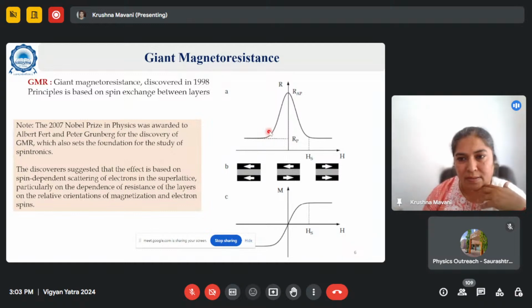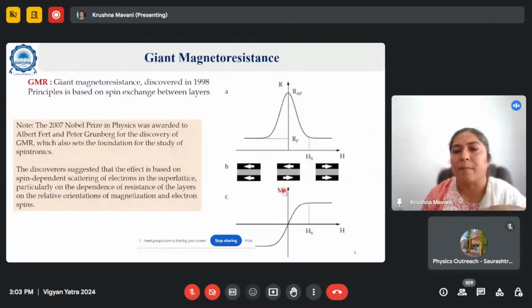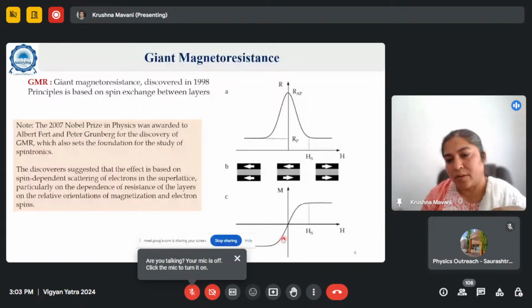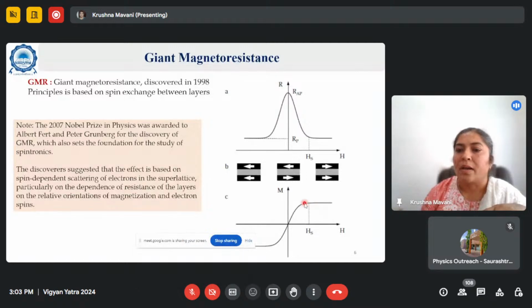rise in the resistance. You can see the vertical axis is rising up and showing a peak, and then going down again as you change the magnetic field. So this is basically like hysteresis. You can see this is your zero here in the center. If you increase the magnetic field towards the higher side, you can compare with the magnetization curve shown here. As the spins get more and more parallel, magnetization is rising. At the end, you all know that the magnetization gets saturated at a certain value of external magnetic field. You reverse back, and in a soft magnet, it will come back along the same path.